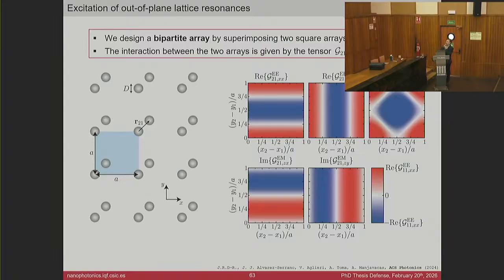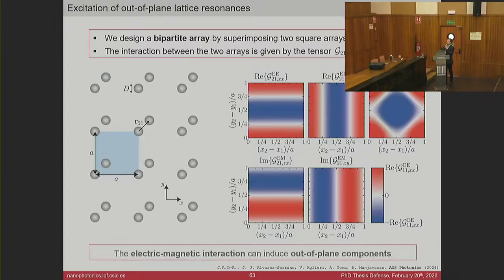And in particular, apart from the xy component that I was showing, you also have an xx. So you have to optimize this interaction at the same time for both components. And this happens, I think I show it here, for these 4 configurations. So it is crucial that the particles lie at those relative positions to sustain this mode. And by symmetry, these 4 configurations are equivalent, actually.